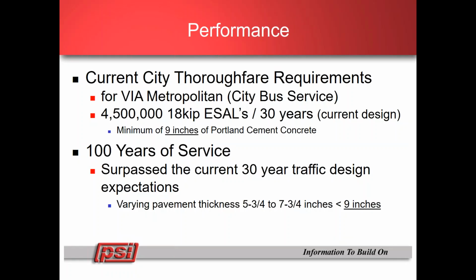The performance of this road, today's city thoroughfare going to design to accommodate via metropolitan bus service would require 4,500,000 18-kip easels over a 30-year design period, with a minimum of 9 inches of Portland cement concrete. Belknap Place has been in service for 100 years. It's surpassed the current 30-year traffic design with varying pavement thicknesses, clearly less than the 9 inches and in the range of 5 3/4 to 7 3/4.